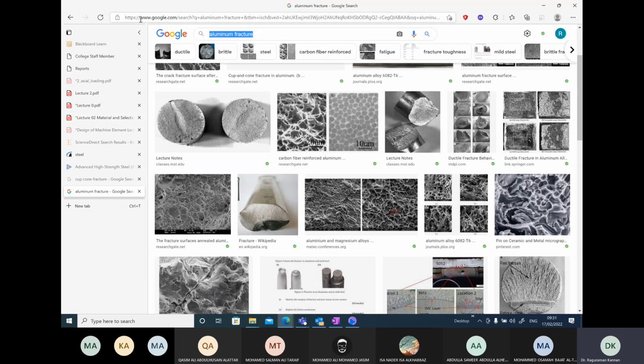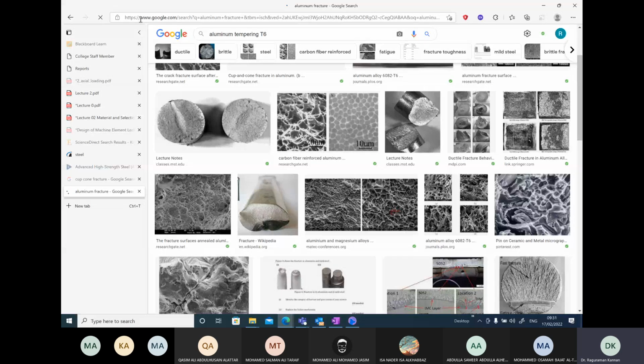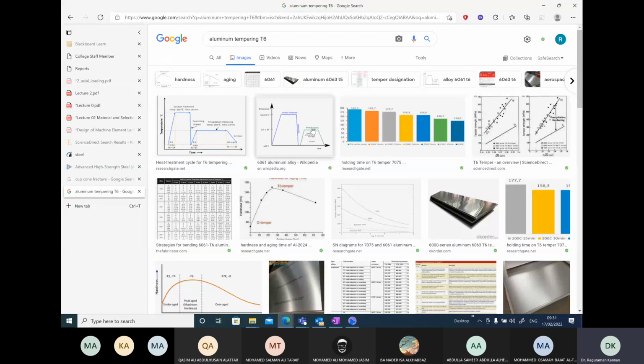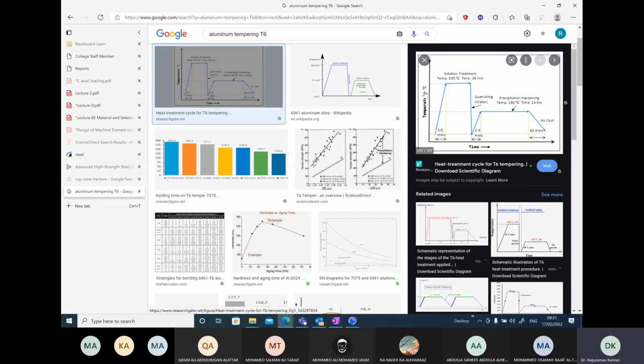Let's check aluminum. Tempering, maybe I use T6, maybe they give a curve. So you can see here 6061 aluminum alloy, T6 tempering heat treatment process. So this is how you have temperature. On the x-axis you have time, and it gives you exactly how to do the heat treatment. 3 to 5 minutes. You increase the temperature from room temperature all the way, you go to 535 degrees centigrade.